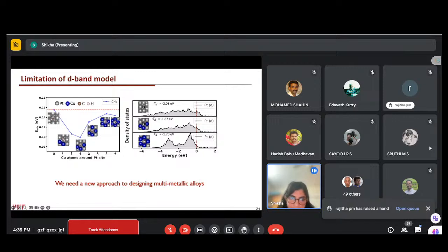But after a certain time, our curve bends off. So now we are losing the adsorption energy. So it is a contradiction with the D-band model. So what is happening now? If you see the density of states for platinum, the clean platinum site, and when we change the surrounding, we see here we have the anti-bonding states, unfilled states. Here we also have unfilled states. But when we add more and more copper around the site, you can see that the shape of the D band, the D states, would change significantly.